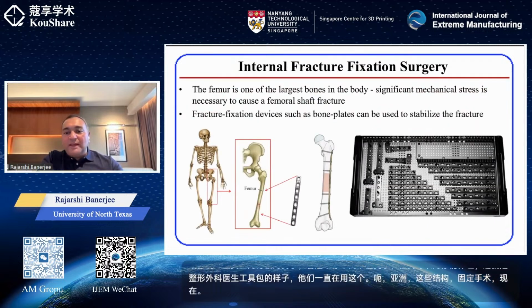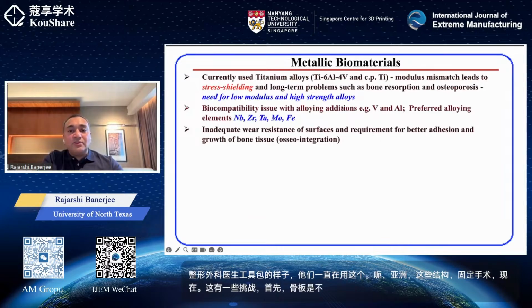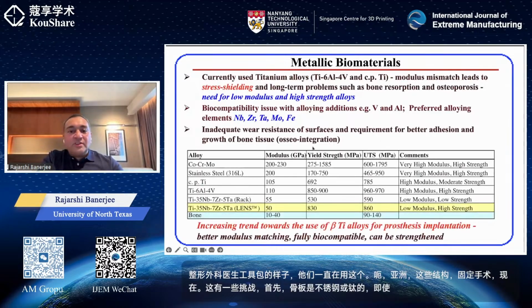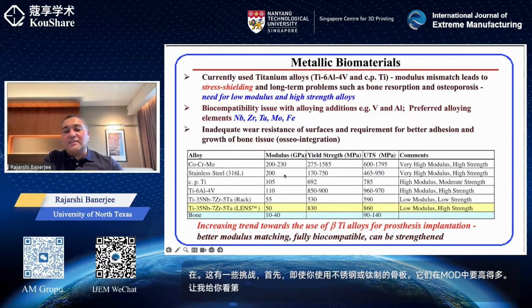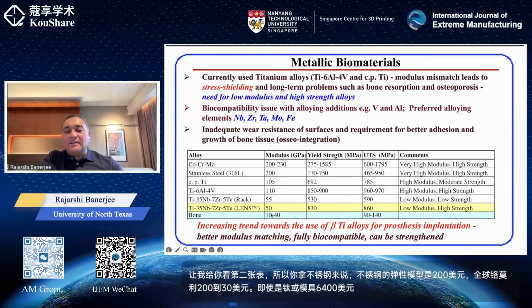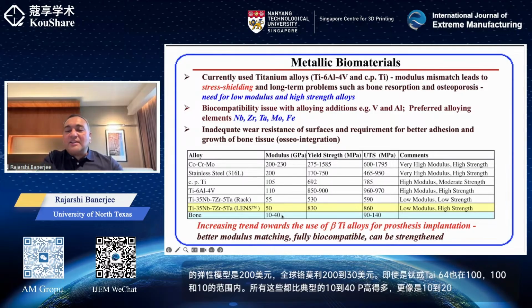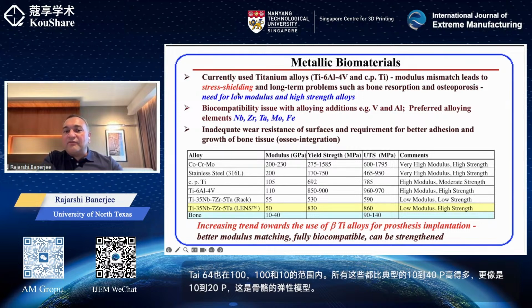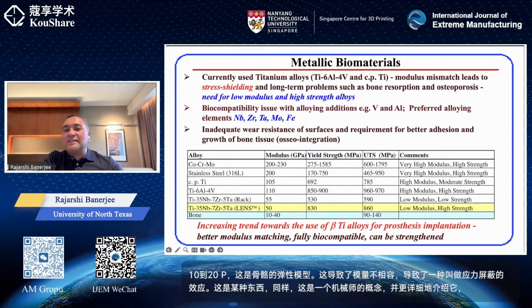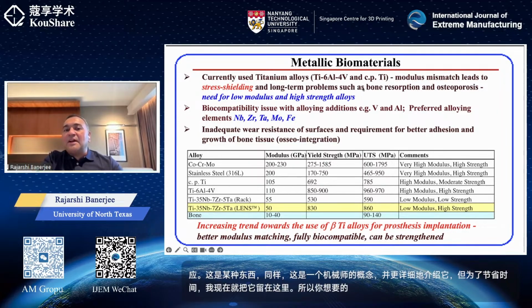First of all, the bone plates of stainless steel or titanium, even if you use titanium, are much higher in modulus. Let me show you the second table. If you take stainless steel, the elastic modulus of stainless steel is 200 odd. Cobalt, chromium, moly, 200 to 230. Even titanium or Ti64 are in the 100 to 110 range. All of these are way, way higher than the typical 10 to 40 GPa, more like 10 to 20 GPa, which is the elastic modulus of bone. This results in a modulus incompatibility that leads to an effect called stress shielding. And this is a mechanics concept. I can go into it in more detail, but in the interest of time, I will just leave it for now. So what you want is better compatibility between the metallic implant and the elastic modulus of the bone. So you need newer alloys.